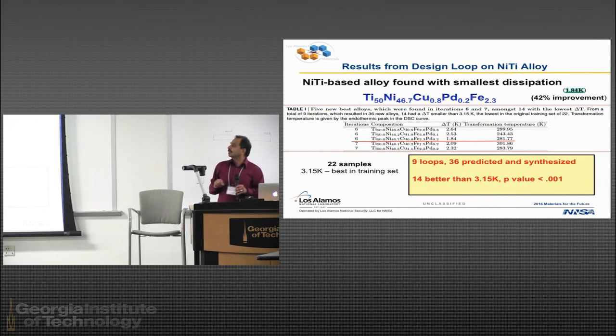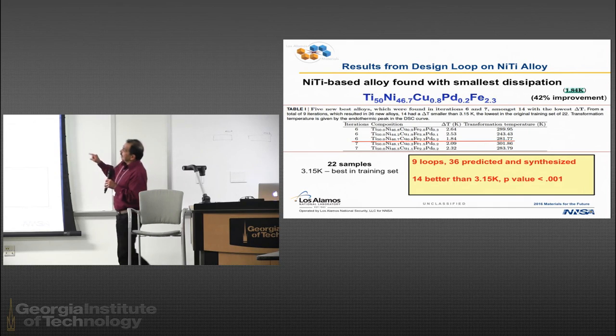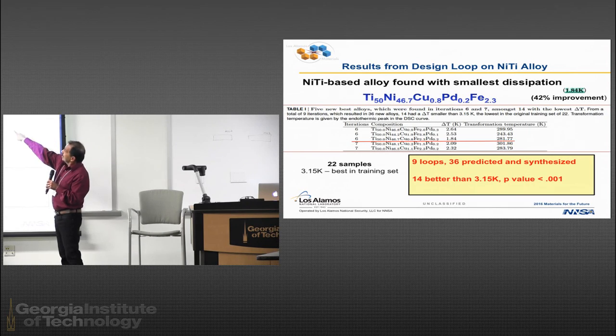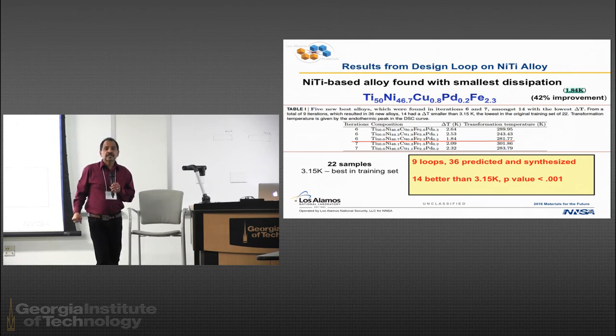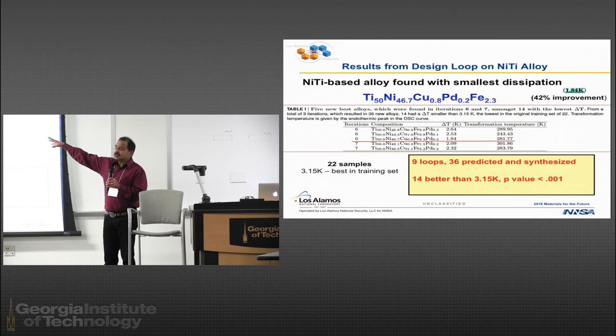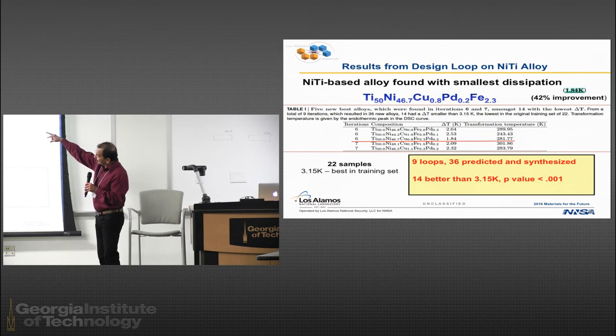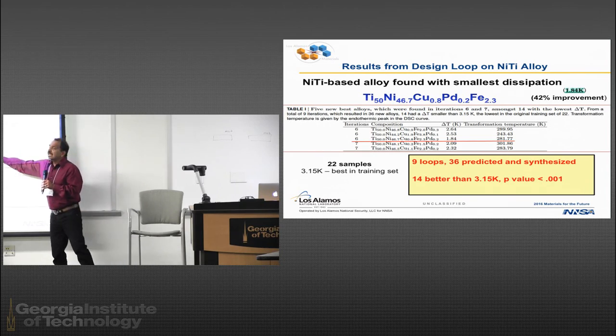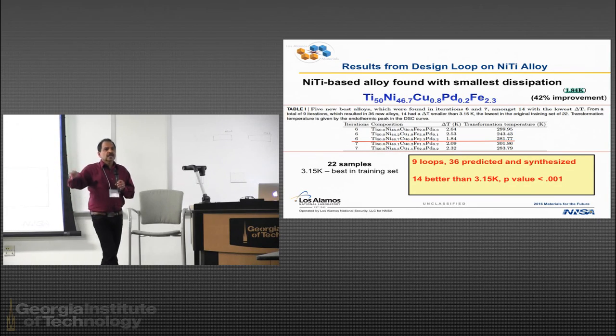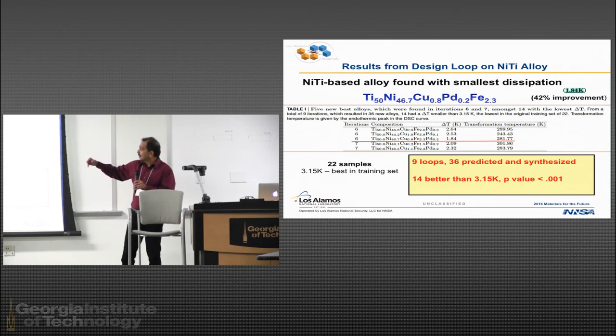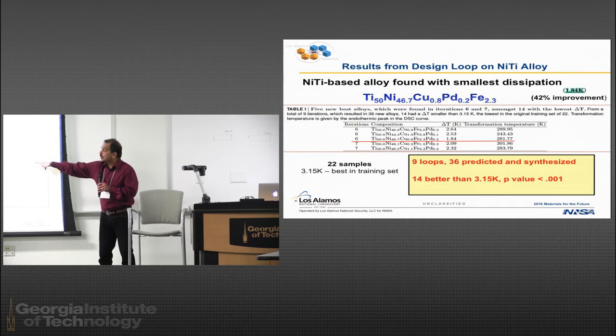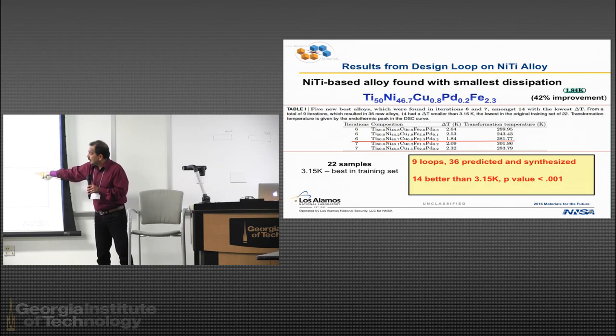So this is the result that we got from our study. The alloy that we found, which had the smallest thermal dissipation, is right there. I certainly wouldn't have been able to find that otherwise. And we got it in the sixth iteration. In our actual exercise, we went through 9 loops. We made 36 predictions because we were giving 4 each time. So we synthesized 36 compounds.